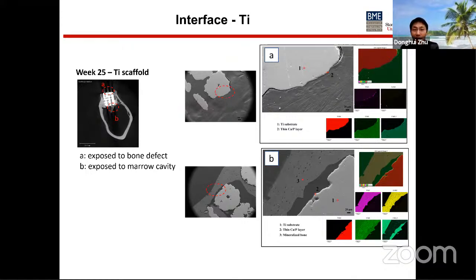This is a titanium control after 25 weeks. At the defect region A, a thin layer of calcium phosphate compound was observed on the surface. In the cavity region B, there is also a calcium phosphate compound layer on the surface, but some mineralized bone is partially connected with the titanium scaffold, indicating good osteointegration.